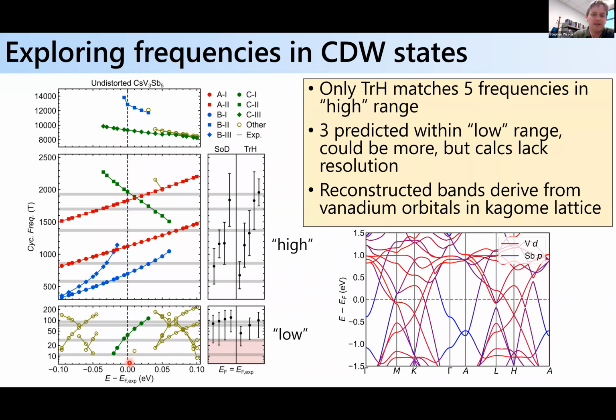What I've shown here is the Fermi level, which can be adjusted plus or minus relative to the experimental value. This experimental value was benchmarked to STM and ARPES data on our samples from the same batch, which is consistent with one another. If you look at the Fermi level from the experiments, you can count the frequencies that arise. The left panel shows the frequencies you expect from the undistorted structure, which we know has deficiencies: 1 missing high frequency orbit, and obviously 3 missing in the low frequency regime.